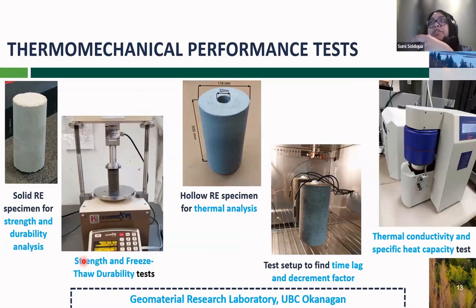Now we are coming to a slightly newer component that we want to address, the durability part. Still, we want to use a small amount of cement rather than the higher percentage of cement that modern rammed earth products use. But we want to see, can we use this fly ash and look into the thermomechanical performance? And we have used a modified mold to test those kinds of parameters that are important from the durability point of view.